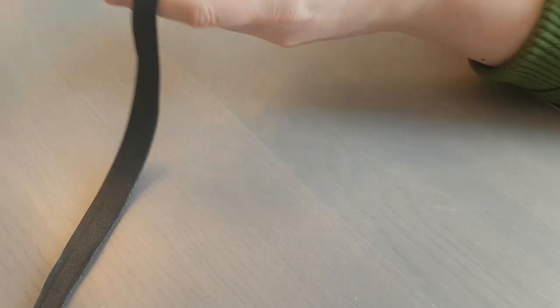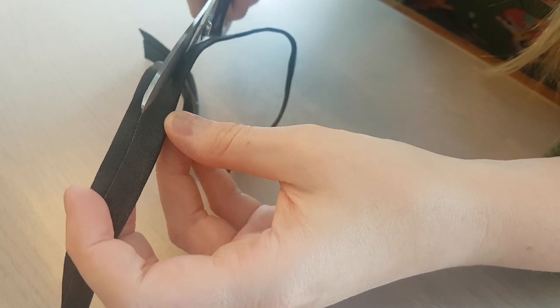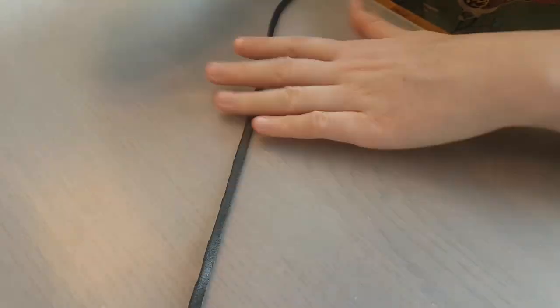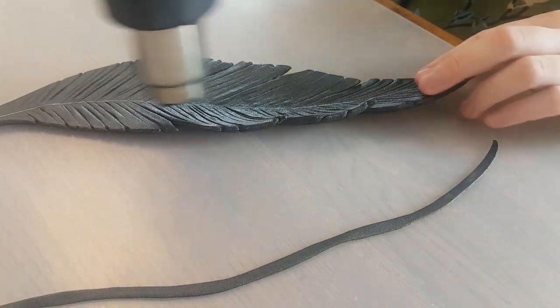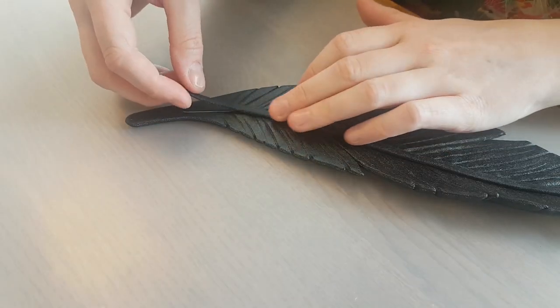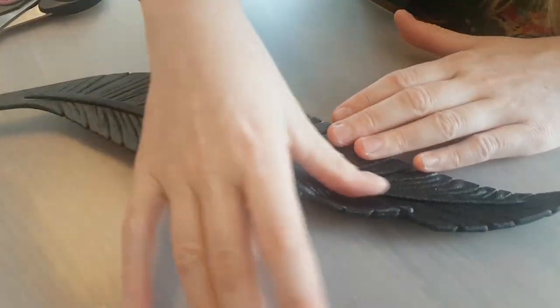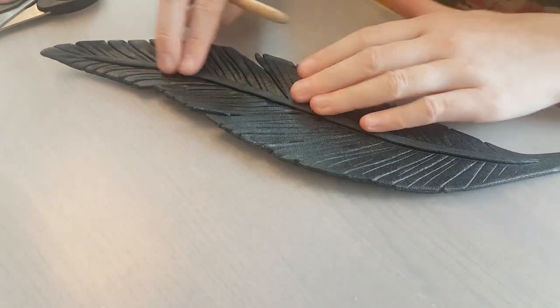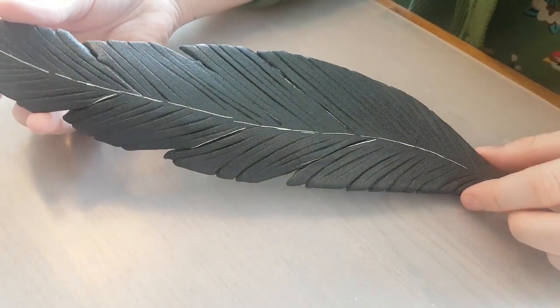We still need a thin raised line in the middle of the feather to make it look more realistic. To do this, I actually use scraps of Worbla — this is a double layer of Worbla that I cut off around the edges of the feather earlier, and now I have a nice thin line. I need to heat up the line and also the feather to make both pieces of Worbla sticky. It's very important that you heat up both the surface that you want to stick it to and the piece that you want to stick to it, because otherwise it can fall off. Then I just press the line onto the feather and use some pressure to really stick it on. I smooth out the edges a little bit using my clay modeling tool and also just my fingers. The other side of the feather still needs this line, and then it's mostly done.